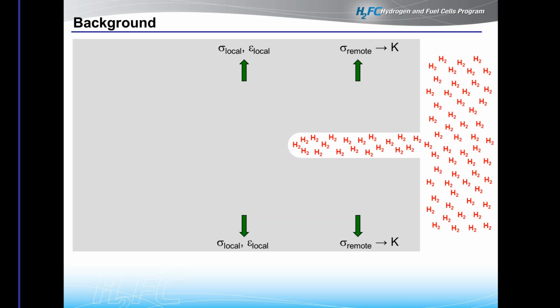So first, the hydrogen has to be able to transport down the crack tunnel, essentially reaching the crack tip, so basically it becomes a supply issue. Can that hydrogen get to the site where it needs to, or where it may cause embrittlement? The second step is that the hydrogen is in diatomic form. It needs to dissociate and chemisorb on the surface. This is just one of the possible limiting effects, but hydrogen does need to dissociate onto the surface. And then it can finally absorb into the material and move to these regions of higher stress and take part